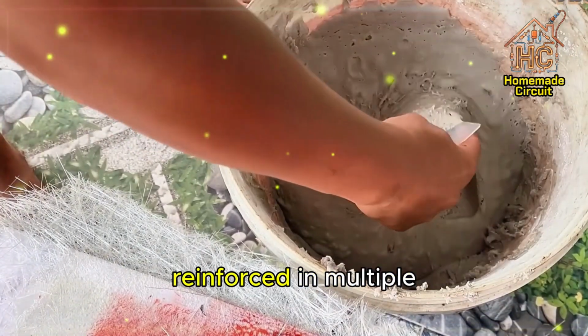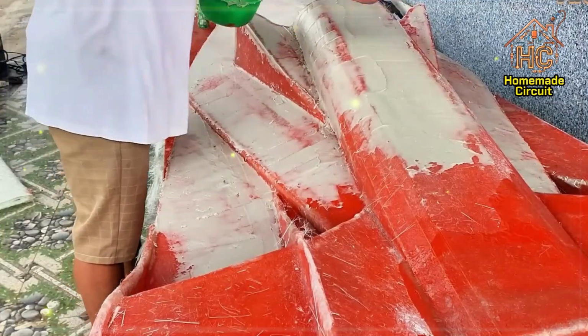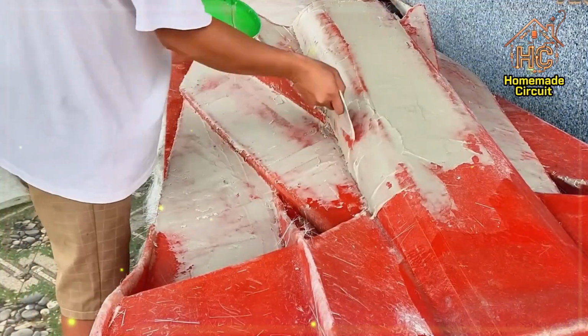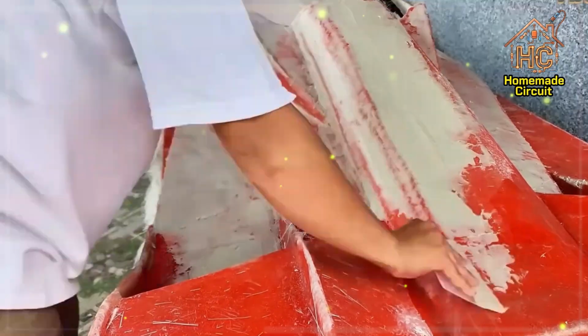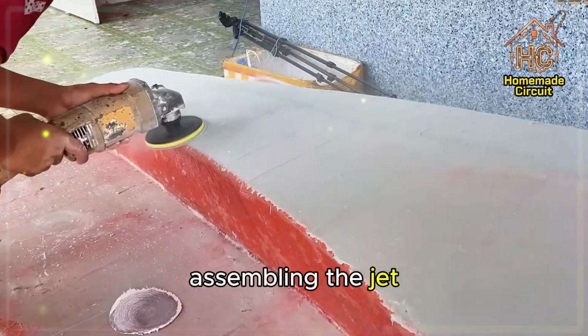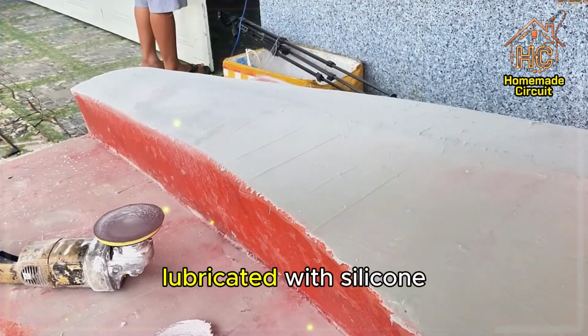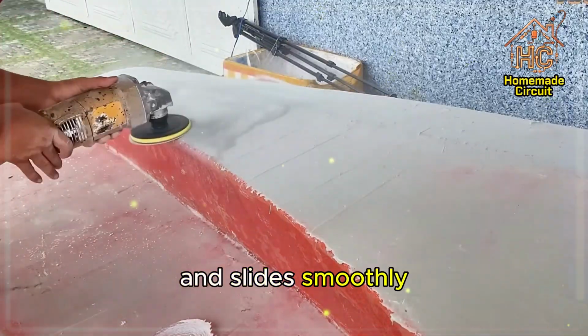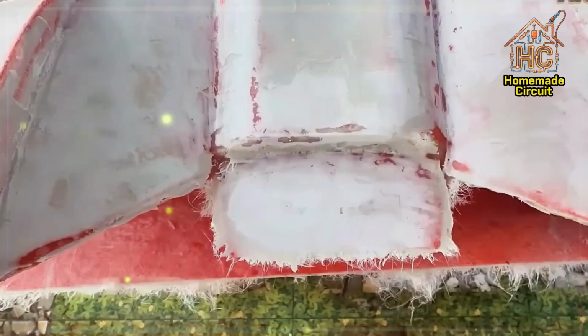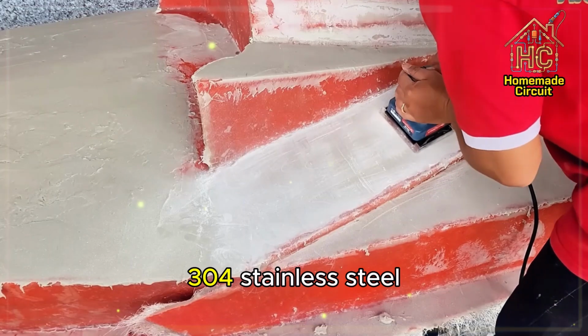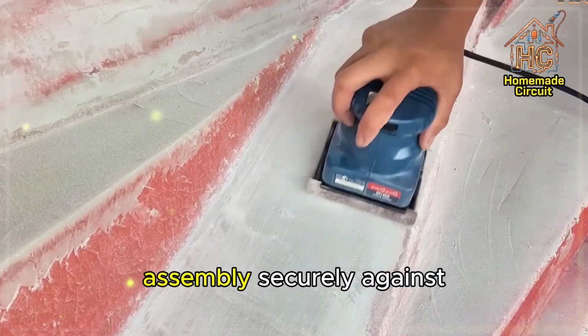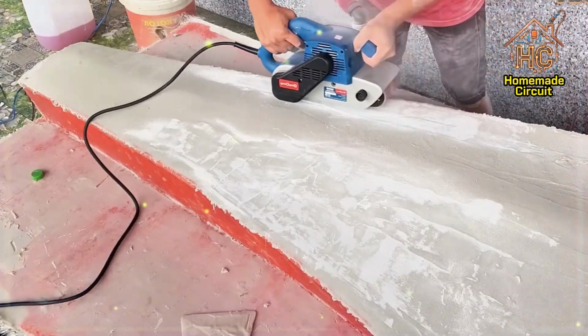Fiberglass is once again reinforced in multiple layers over the stringers, forming a unibody skeletal frame. Assembling the jet pump, the waterproof rubber gasket is lubricated with silicone grease and slides smoothly into the tail mount. The corrosion-resistant 304 stainless steel bolts are tightened with a torque wrench, pressing the jet assembly securely against the hull.